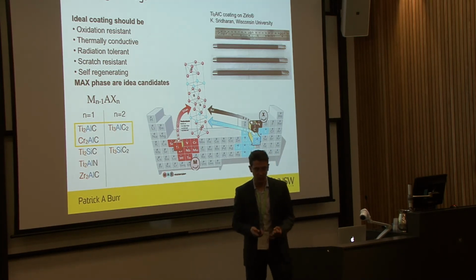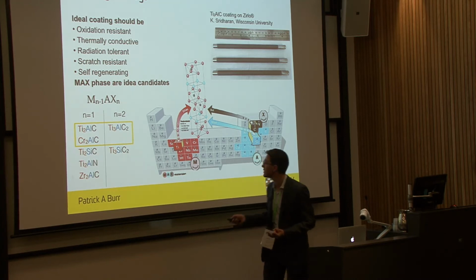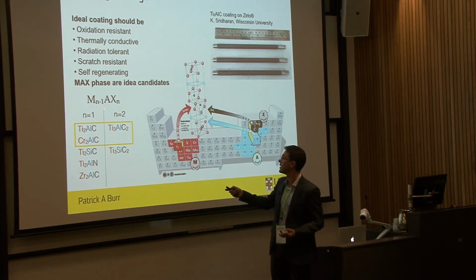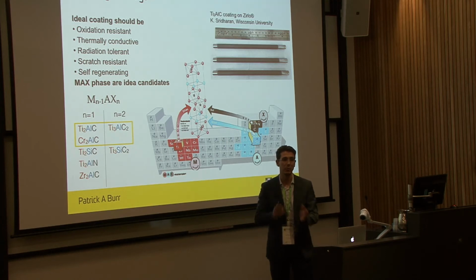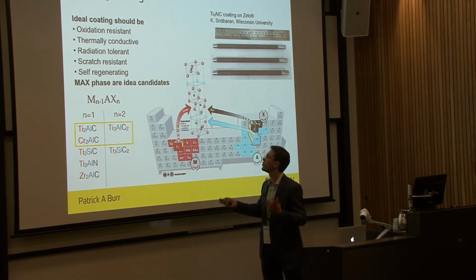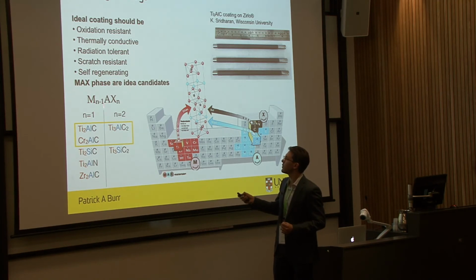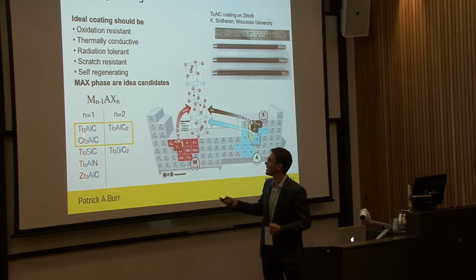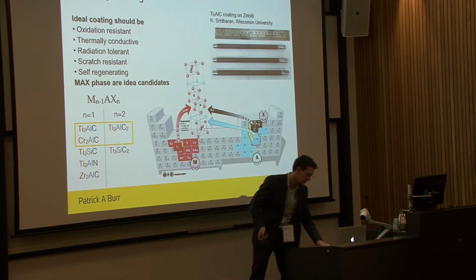Because of the constraints on neutronics, and because we want oxidation resistance, we're limited with A being aluminium, because when you oxidize something that contains aluminium, it forms a nice alumina layer, which is protective. X being carbon, because if you use nitrogen, then you've got a problem of activation, though you could get around those. And then you've got a little bit of play with M. In particular, titanium aluminum carbide and chromium aluminum carbide have been identified as very good candidate materials.